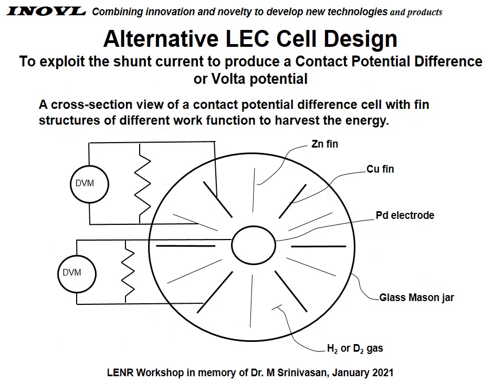Here's one of the LEC cells that I talked about earlier. In this case, we have the Pd-coated electrode in the center, and the counter electrodes are alternating fins of copper and zinc. This test was conducted in a glass mason jar, which is about 4 inches in diameter. The reason we wanted that was, if it was particulate ionization, we wanted to be out in the Bragg curve where the bulk of the ions are produced.